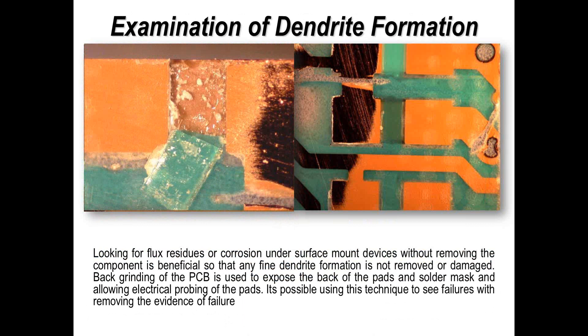Doing that on a board that has been soldered and not cleaned, versus one that has been cleaned, shows the difference in performance. I also use this test when I know there's corrosion or a problem. If we take boards and put them into environmental tests — perhaps in an oven with some humidity — we can see the reaction just by doing the same grinding and inspection technique. It takes a little bit more time and you need an oven, but you don't have to have the sophisticated tools associated with surface insulation resistance. There's no point spending money and effort unless your process is pretty much 95% effective.